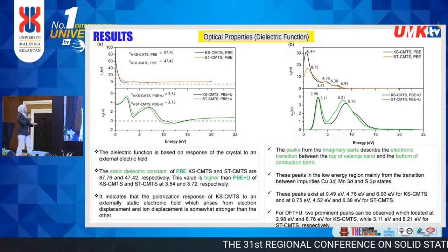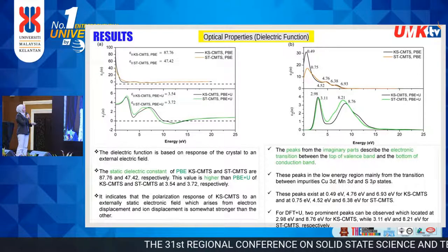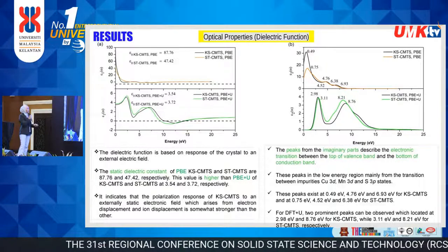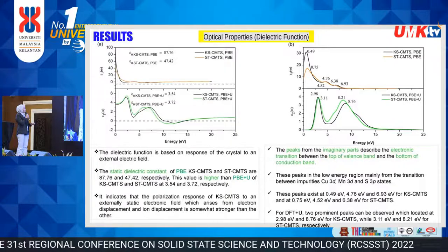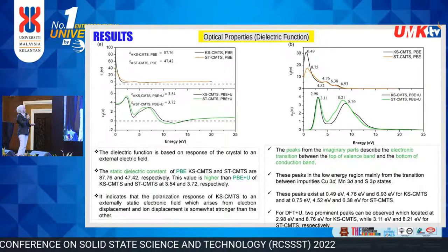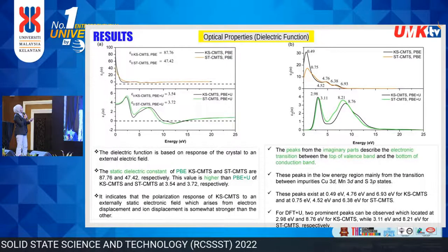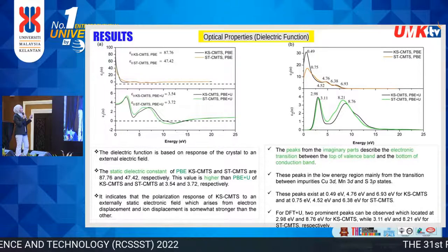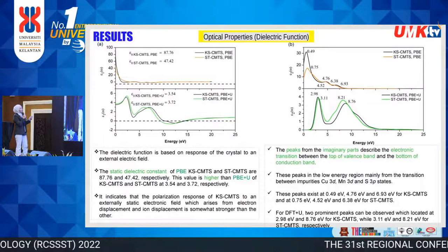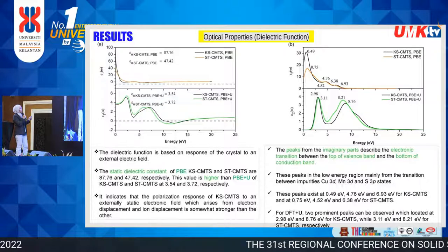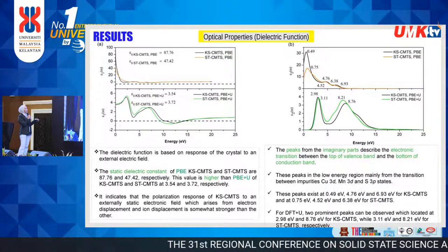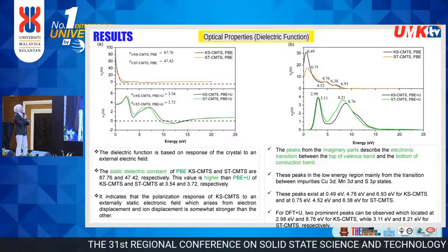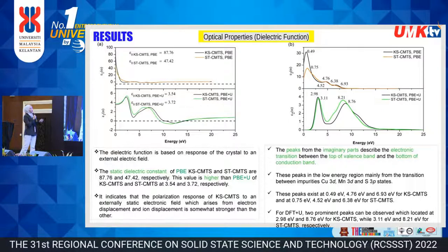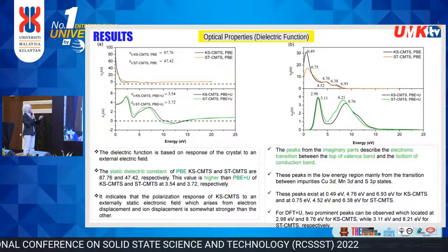So this is the optical properties for the dielectric function. It is based on the response of the crystal to an external electric field. The static dielectric constant, epsilon naught, of PBE, the standard DFT, is higher than that of PBE plus U, which is the DFT plus U static dielectric constant. So for the graph over there,